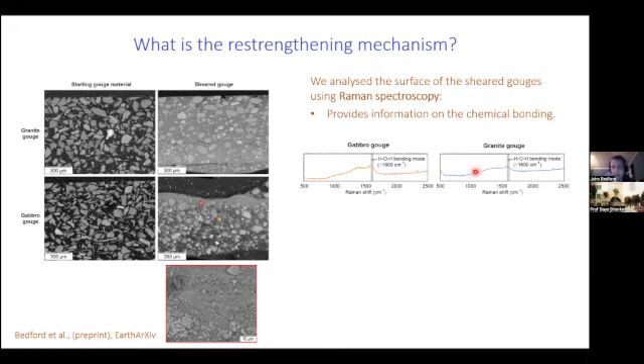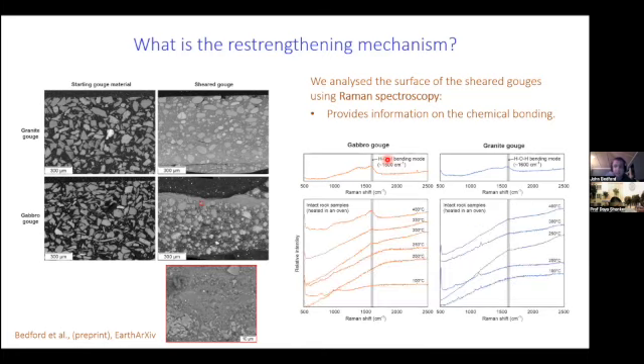And what we found in both materials is we get a small broad peak in the spectra, at a wavelength of around 1600. And what this Raman peak corresponds to is a particular vibrational mode of water that is absorbed on the surface of the sheared materials. And this is something that we don't see in the starting materials or gouges that are sheared at low velocity. So what I did was I took some of the starting materials and heated them in an oven to different temperatures, and then removed them from the oven and let them cool in the humid atmosphere, similar to how the fault gouge layers cooled within the experiment.